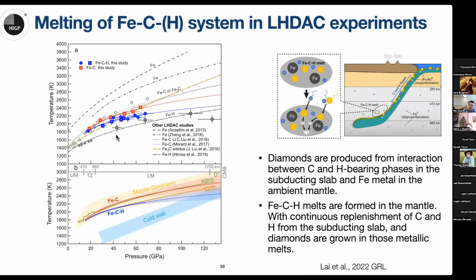So we summarized all of our experimental results, which show the melting temperature of the iron-carbon system and the iron-carbon-hydrogen system. We can see that by alloying carbon with iron, you lower its melting temperature, but by adding hydrogen to the system, you can lower the melting temperature even further.